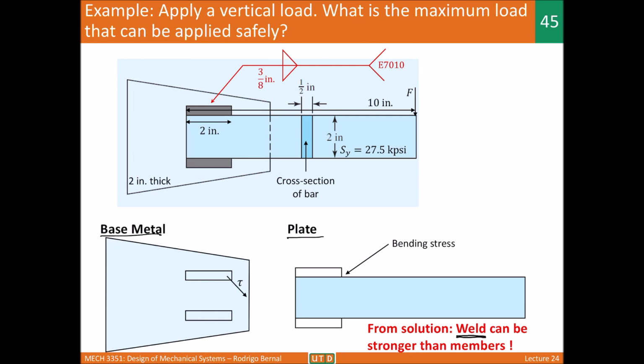So if you have a welding joint and it fails, what you will find a large percentage of the time is that the joint doesn't fail because the welding material is failing. It fails because either one of the plates broke or some component in the joint failed aside from the weld. The weld itself is very, very strong. And it's a good thing because we want to have a permanent joint, but it just highlights the fact that you need to calculate the stresses in every single component of the joint, just like we did for shear joints in bolts and fasteners.